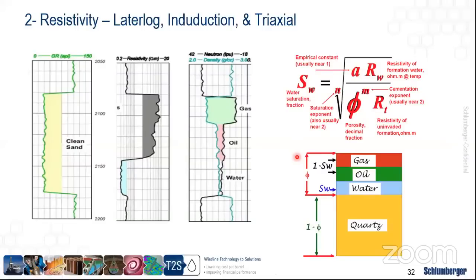So what happens in the basic formation evaluation or quick look is that we look at the plain gamma ray, and then we look at the resistivity. We identify where there's high resistivity and low resistivity. Typically, we'll be assuming high resistivity for simplicity at this level. That high resistivity would represent hydrocarbon, and low resistivity would represent water. And once we identify where our high resistive zone is, we go cross-check the neutron porosity and bulk density in order to see the separation between them, in order to identify, for example, gas or oil. And then typically for water, the neutron porosity and the bulk density data should be overlaying.